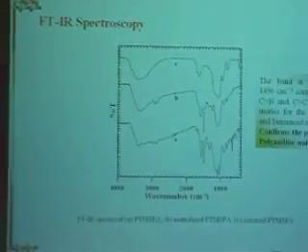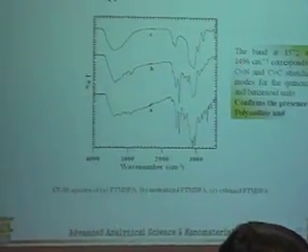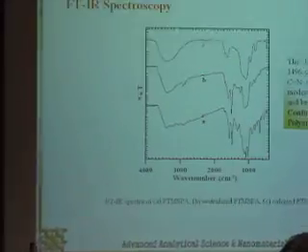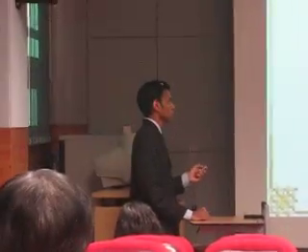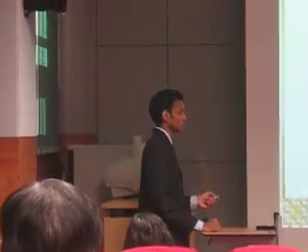This figure shows the IR spectrum. From the figure you can see peaks at 1572 and 1496 corresponding to the quinoid and benzenoid units present in the material, confirming the presence of polyaniline units in the system.